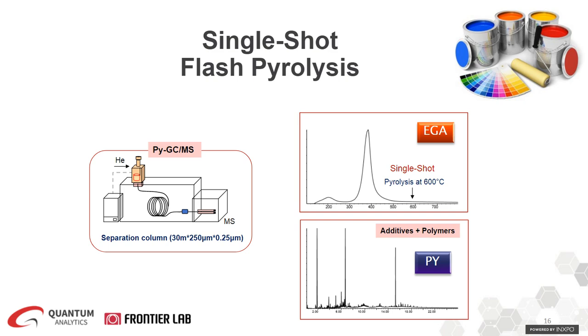It really depends on, after you run your EGA, your evolved gas analysis, you have to figure out the optimal setting. So if you want to do thermal desorption, you have to figure out the optimal thermal desorption or the flash pyrolysis. But in flash pyrolysis, it will be one single set point for polymers. But in a double shot, for example, you program it from 100 to 250 C, and then you'll do another shot for flash pyrolysis at 650 or 550 C. So it really depends on your EGA thermogram.